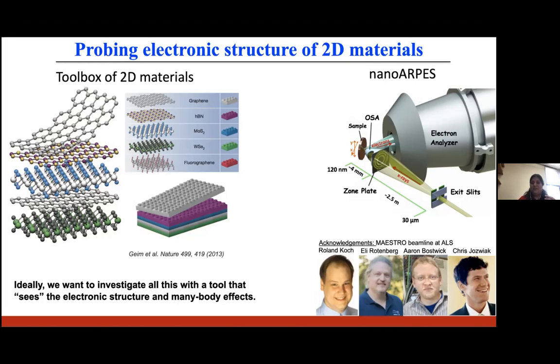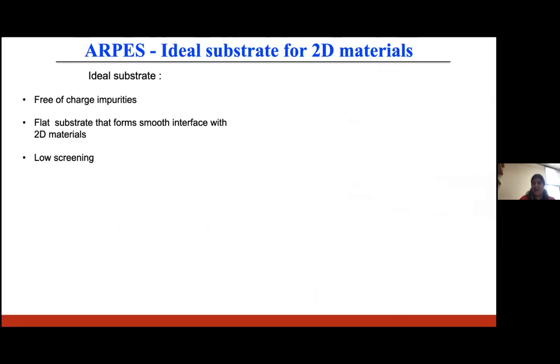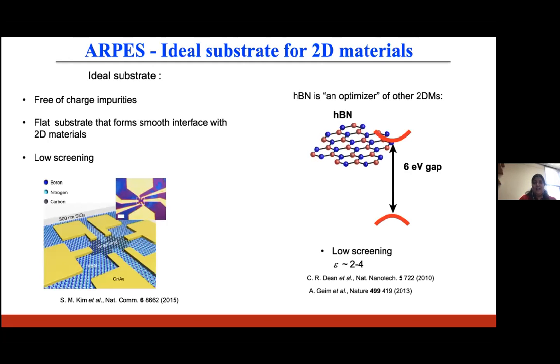And so now the first step for doing ARPES or nano ARPES measurements on these 2D materials is to find a substrate that would be ideal for doing these measurements. And it turns out for doing our ARPES studies, an ideal substrate should have these properties. It should be free of charge impurities. It should be a flat substrate so that it forms a very smooth interface with the 2D material and doesn't cause additional scattering. And it should have low screening so that you can obtain useful information. And from the transport measurements, we know that HBN is a very good substrate for 2D materials. The only problem is that it has a large band gap of about 6 eV.